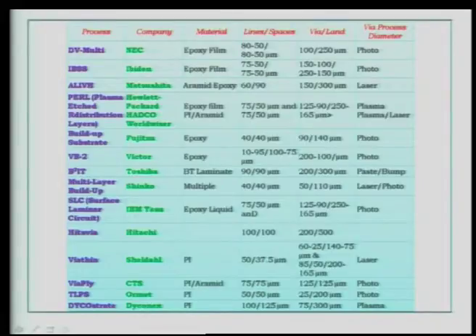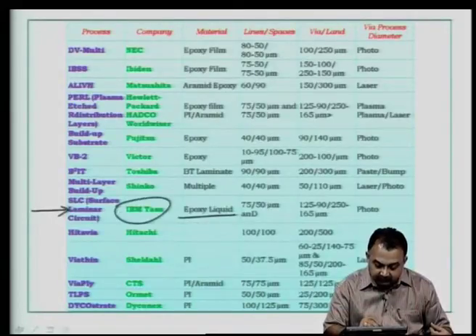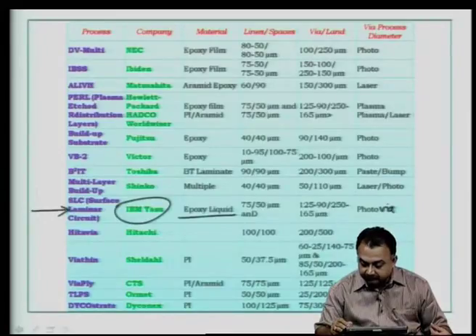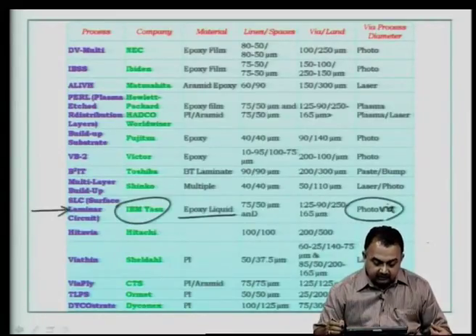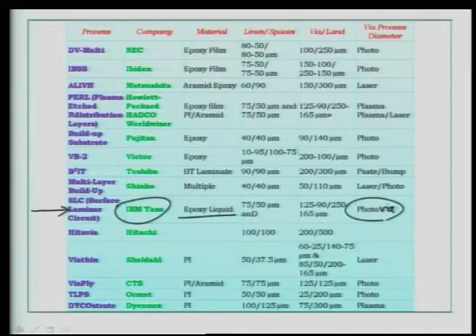of. Now, here is a list of companies which has been picked from various sources. If you look at this, probably the starting point is the SLC, surface laminar circuit, which used epoxy liquid from IBM Yasu, and this is a photo via process. And then came up various processes from different companies like Fujitsu, Toshiba, Hitachi, Sheldal. Sheldal came up with a readily available substrate that can be used for laser drilling. So, you did not have to worry about thickness control of the materials, and you can see that lines and spaces like 50 to 37.5 microns have been